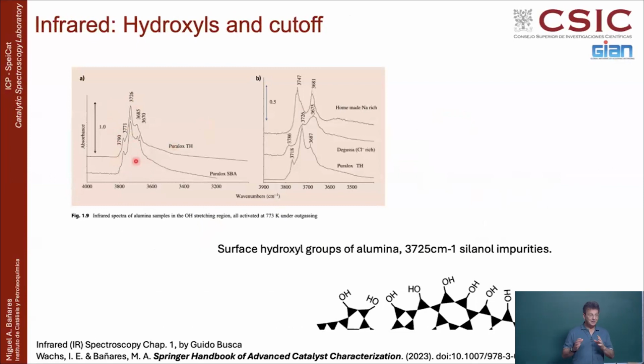Well, silica is kind of a different material compared to others. Usually, most oxide surfaces have up to 7 hydroxyls per square nanometer, which physically is like a monolayer. I mean, in one monolayer, you can put up to 7 hydroxyls, so the whole surface is hydroxylated. But silica, depending on the silica, some silica is made at very high temperature, like fumed silica at 1,000 plus degrees. It has a very high surface area, but it's hardly hydroxylated. It has like 1 hydroxyl per square nanometer.